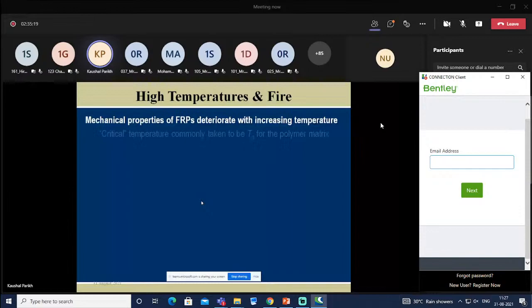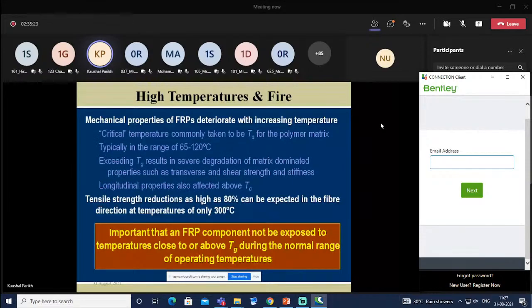So the mechanical properties of FRPs also deteriorate with increasing temperature. How? Let us see. The critical temperature is commonly taken to be Tg for the polymer matrix, and it ranges between 65 degrees and 120 degrees. See, 65 degrees right now we can say is not that high. Yes, it is definitely high, but in our Indian environment, at certain places the temperature may reach 45 or maybe 50 degrees. So 65 is not that far. Tg results in severe degradation of matrix-dominated properties such as transverse strength and stiffness, and finally the longitudinal properties are also affected and the bond is severely damaged.